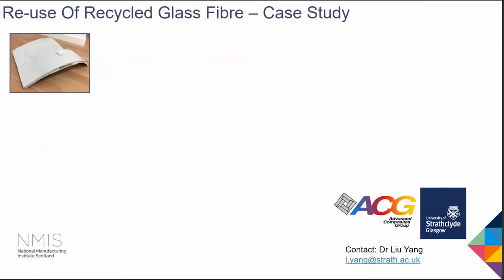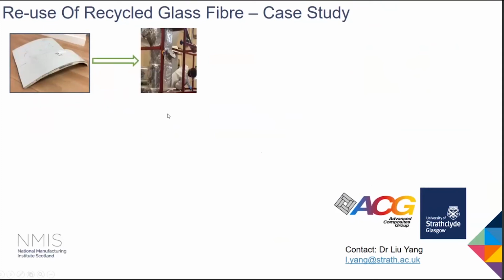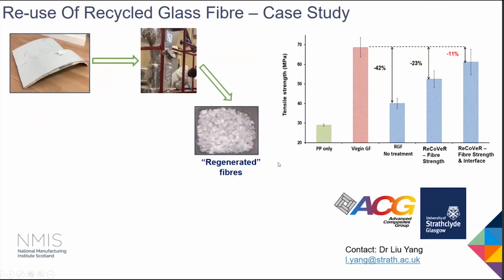Lots of research work has been done by the Advanced Composites Group at the University of Strathclyde. The first step is similar: collect the waste pieces from the end-of-life wind turbine blade, and do the size reduction to make sure it can fit into the ACG's advanced optimized fluidized bed recycling process. Through a project called Recover, ACG developed the patented sizing to enhance the fiber strength and improve the bonding system. With the regenerated fibers, you only see an 11% reduction in tensile strength compared to the virgin glass fiber products.